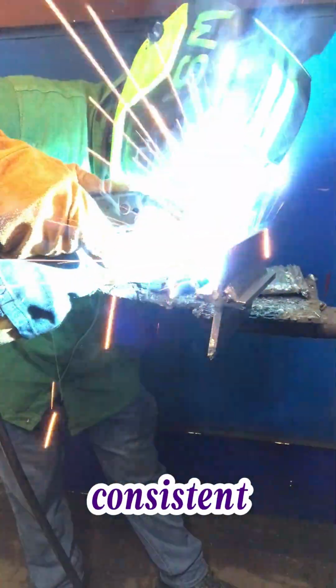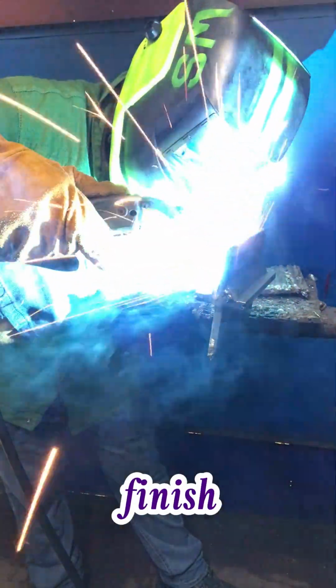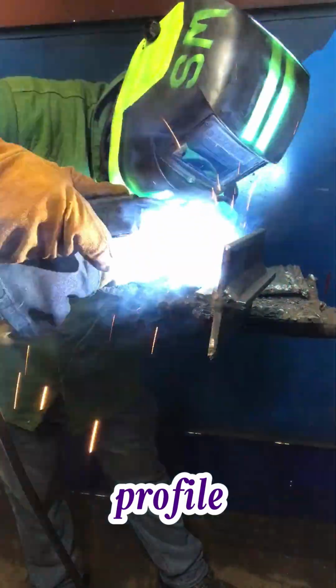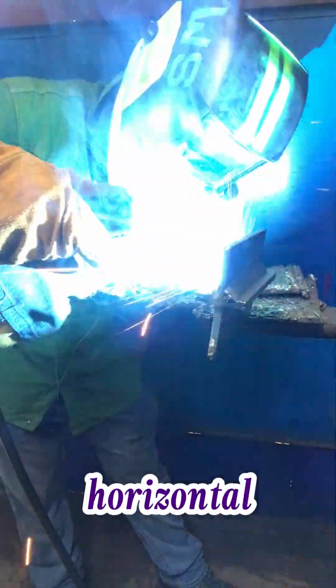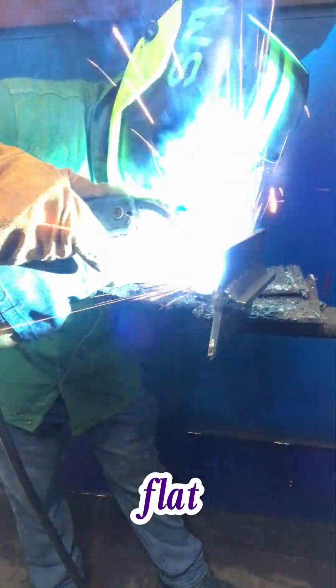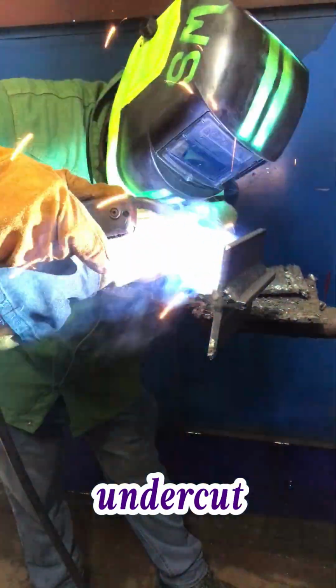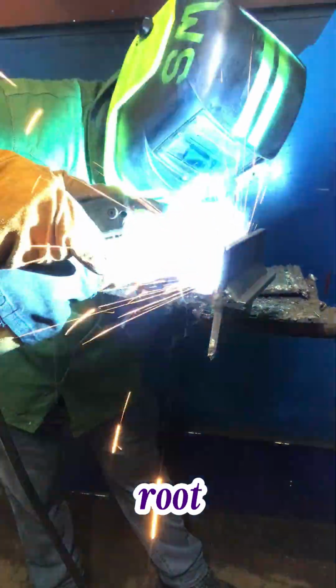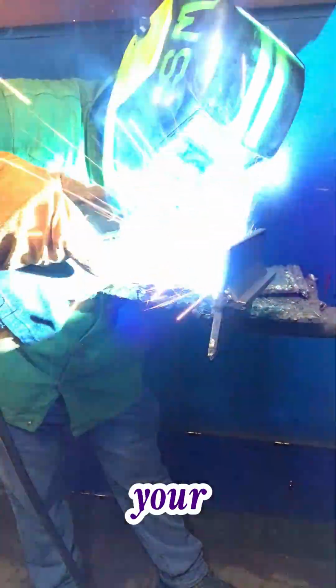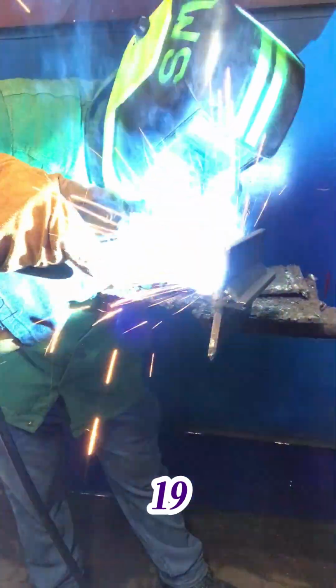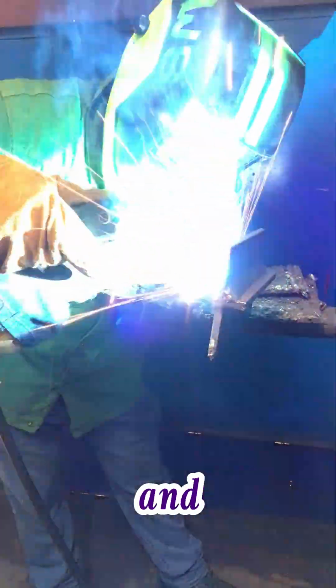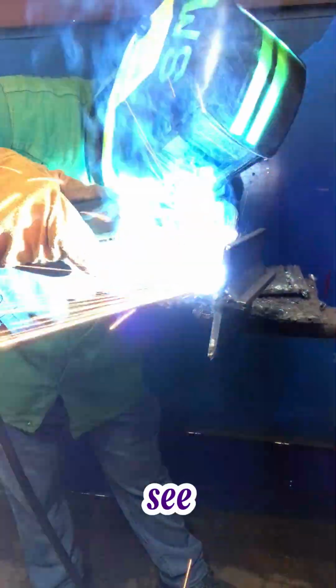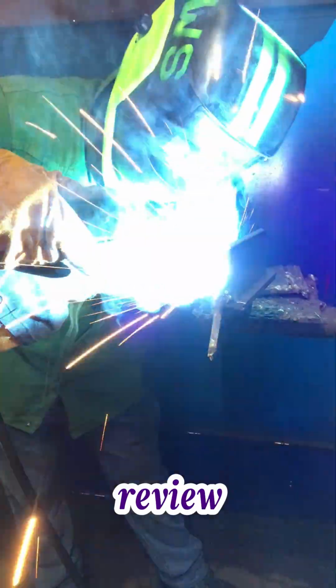NC2 visual inspection criteria. Uniformity: consistent bead width from start to finish. Leg length and profile: equal 6mm legs on both horizontal and vertical plates with a flat to slightly convex profile. Defect-free: zero undercut, no porosity holes, no overlap on the bottom leg, and full root penetration. Grab your safety gear, set your voltage to 19 volts, prep your plates, and start your practice plates. See your instructor for your midpoint review.